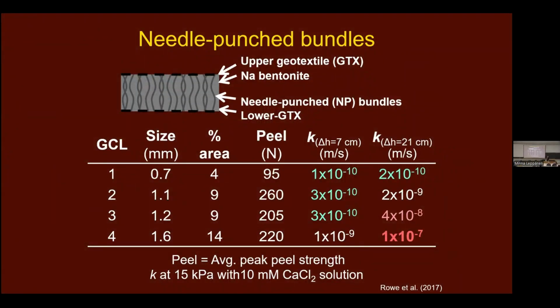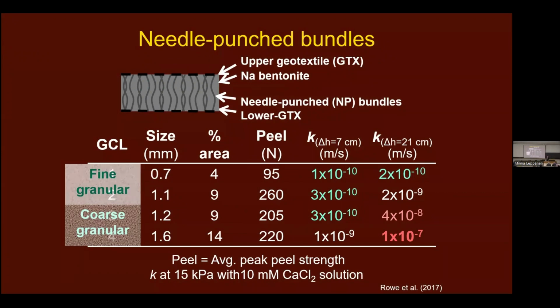Now increase that to 21 centimeters. Still not a massive gradient. And we've got 2 times 10 to the minus 10 through to 1 times 10 to the minus 7. So 3 orders of magnitude difference in hydraulic conductivity. This is telling us that the history of those specimens combined with what they started like has a significant effect on their long-term hydraulic conductivity. So these last 2, coarse granular bentonite, first 2, fine granular bentonite.